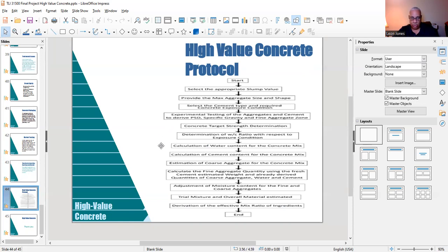I'm gonna determine water cement ratio, the calculation of water cement for the concrete mix, calculation of the cement content for the concrete mix. I have also estimation of coarse aggregate for the concrete mix. And then I'm gonna calculate the fine aggregate quantity using the fresh cement estimated weight, already derived quantities of coarse aggregates, water, and cement. And I'm gonna make an adjustment of moisture content for the fine and coarse aggregates. Then run a trial mixture overall from the overall material that's been estimated. Then I'm going to have a derivation of the effective mix ratio of ingredients. That is my high value concrete protocol.